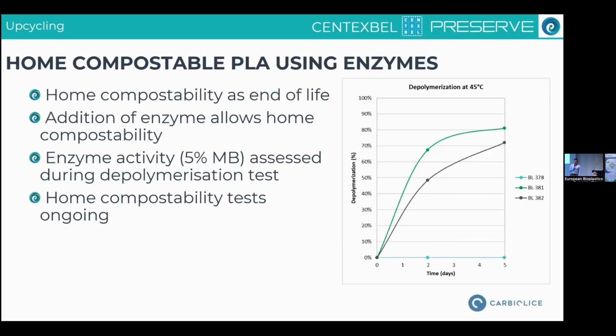And then finally, for the recyclability aspect, we also looked at the home compostability of PLA. The aim here was to add an enzymatic master batch developed by Carbiolice into PLA and see the effect of this master batch on the biodegradation under home compostability conditions. A first assessment was already made with the first batch, and there we saw that most of the enzymes degraded during the extrusion process.